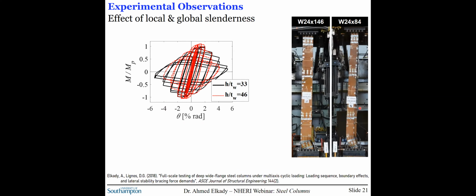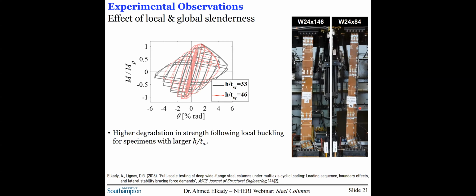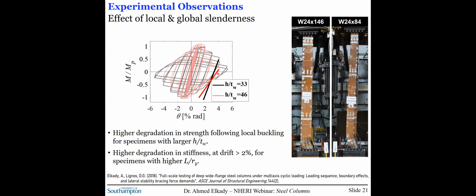We can also, from these tests, evaluate the effect of the local and global slenderness. And as you may have guessed, you are expecting higher degradation in strength following local buckling for the specimens with larger H over T web or larger web slenderness. But also, more importantly, we observe that column specimens that have a higher member slenderness L over Ry tend to lose stiffness, again, at a larger rate, and this happens typically at drifts larger than 2%.